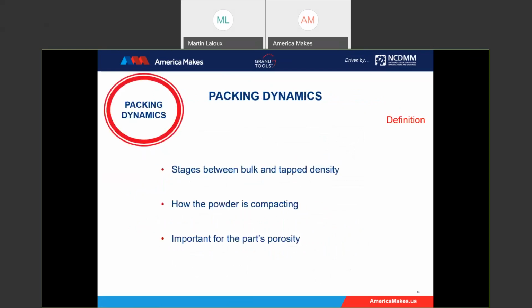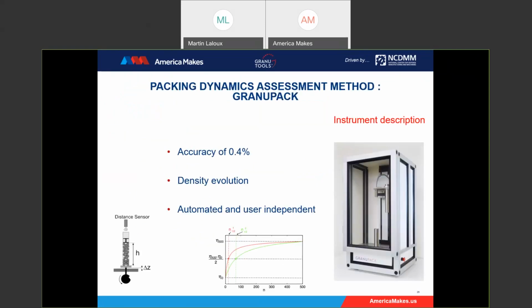So the second key parameter is the packing dynamic. This is the stage between the bulk and the tap density. It's how the powder will pack, and it's important for the part's porosity. So again, the assessment method we use is the GranuPack instrument. For the description of this instrument, we have a distance sensor. It will measure, in fact, the density after each tap. The tap is a 1 millimeter free fall. For this instrument, we have an accuracy of 0.4% repeatability. We will see the evolution of the density.